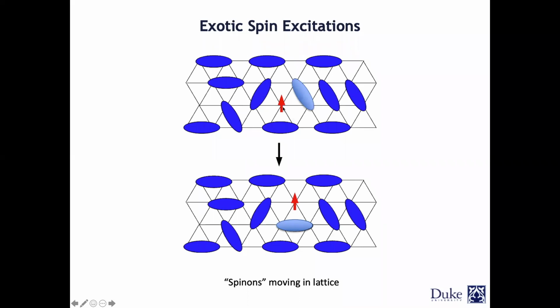It is dynamic in a way that if you consider this bond here, what it can do is that it can break this bond and try to make another bond with this spin here and then free this spin here. So practically it can transform from this state to this state. So you can see that if we try to, for example, probe the spinons or these quasi-particles, which practically, I forgot to say this, sorry, a spinon is practically a spin half without the charge, as you can see here. So when you break this and you try to reform the bond here, then you're going to have this bond, and then this spin is going to be left alone, and this is now the spinon. So practically, if you map in the Q, you can see as a function of energy, there is going to be a dispersion related to the spinons. Okay.